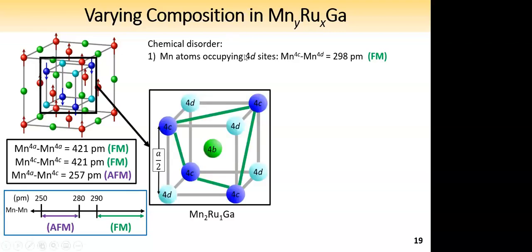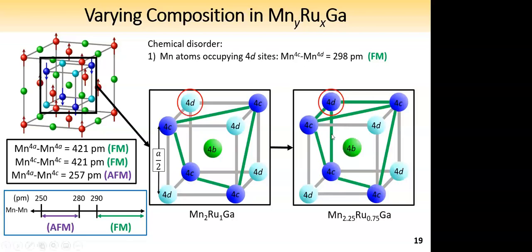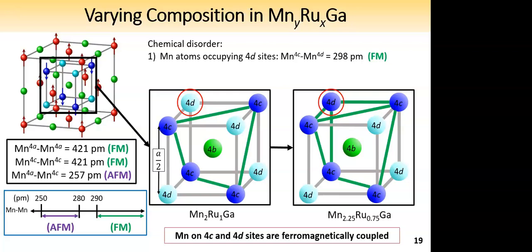The first type of chemical disorder that I will introduce is manganese atoms occupying 4D sites. To do that effectively, I'm going to zoom into the 4C sublattice part of the unit cell, which I'm showing here. This is for the ideal, fully occupied composition, manganese 2, ruthenium 1, gallium. Now introducing some disorder, I have replaced the ruthenium atom with a manganese atom. This would lead to a composition of manganese 2.25, ruthenium 0.75. As you can see, the distance between the neighboring manganese atoms is 298 picometers, which would lead to ferromagnetic coupling. And so this is our conclusion.